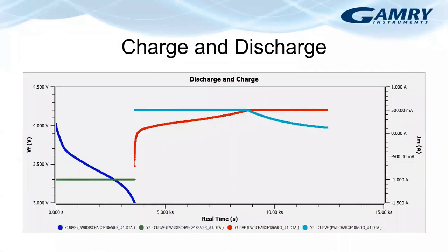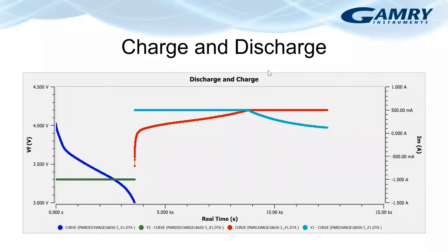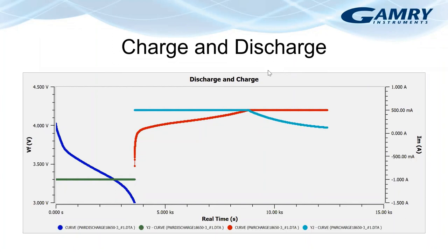So if we go back to the presentation, I've got one I did earlier. Here's a strip chart of the discharge of this battery, followed by the subsequent recharge of it. I did this discharge at one amp. And then I charged it back at 500 milliamps. The total length of time of that experiment was approximately 12,500 seconds or about three and a half hours.